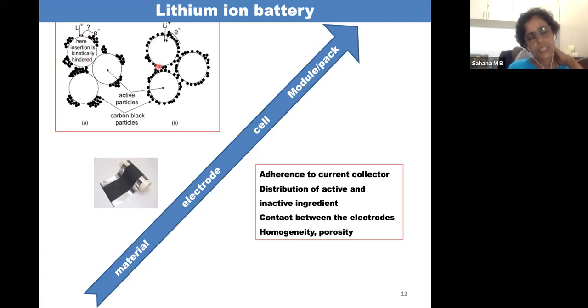Whereas in this case, where the carbon black is uniformly distributed throughout the active material, the distance between lithium ion and electron will be minimum. So it is possible for both lithium and electron to easily transport into the active material. So we need this kind of structure.